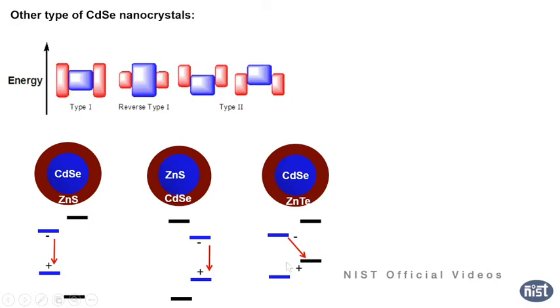But there is another one, type 2, which means two band gaps aligned in a different way, like cadmium selenide here with its valence and conduction band, coated with zinc telluride, whose band gap is different. So when you excite with light, the recombination emission comes not through the direct band gap, but through an indirect band gap kind of thing. So you can get the emission in a different way, and your absorbance and emission are different. That's why people sometimes use type 2, mainly for bioimaging applications, so there is no reabsorbance process and other things.